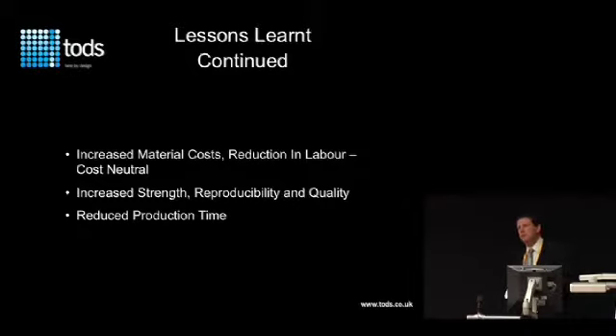Overall, it's cost neutral. The materials are more expensive than, say, the vacuum infusion, but compared with a hand-laminated dome, there's a significant reduction in labour. But really the most important thing is the increased strength and reproducibility and quality. If you've got a hand-laminated dome, then typically the resin drains from the top of the dome down to the bottom, so the thickness varies. You've got two teams of people, one working either side. They tend to work slightly differently, so you can get thickness differences, and also the air content is relatively high. And the other thing we achieve is reduced production time.